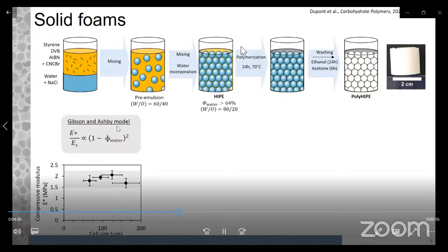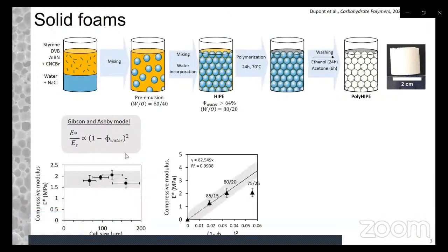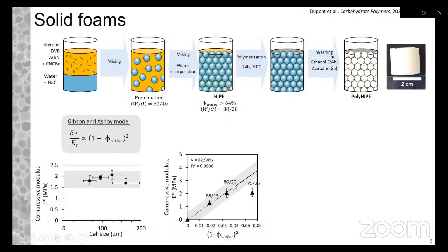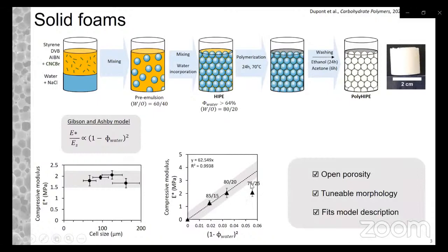This was predicted by the Gibson and Ashby model. If we look at this equation, we tried to change the water fraction, increasing it to 85% and decreasing it to 75%. What we can see is that it fits the model except for low densities. So in the end, we obtained porous solids with an open porosity, which means that all our pores were connected, with a tunable morphology in terms of cell size but also of density, which fits quite well a model description.